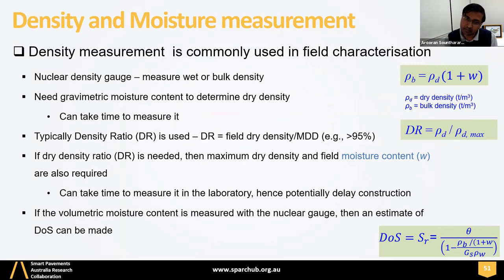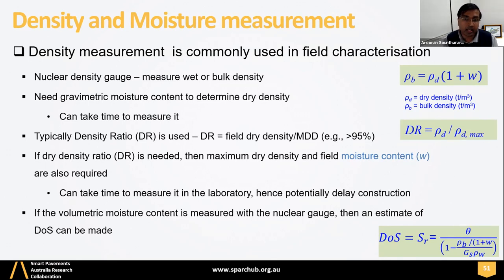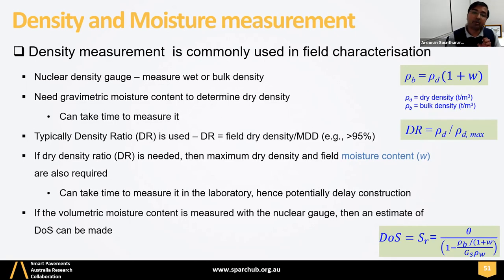However, the accuracy is subjective, depends on the person and how you position the NDG device and the depth at which you test the material. This contributes to erroneous calculations or measurements. And then typically the quality control criteria uses the density ratio, which is more than 95% relative density. And if we measure the volumetric content more precisely using this device, then we would be able to calculate the degree of saturation. Remember, why do you need degree of saturation? Well, we have to make sure that the pavement is dried back to 60% or 65% degree of saturation, which is a quality control before they put the seal.